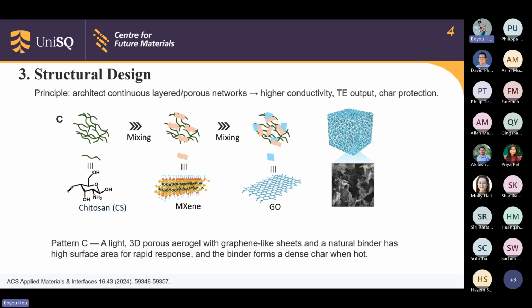In pattern C, a light aerogel provides high surface area and many conductive contacts, so small thermal changes are captured quickly. When heated strongly, the carbon converts into a dense char that protects the substrate and locks the framework in place.